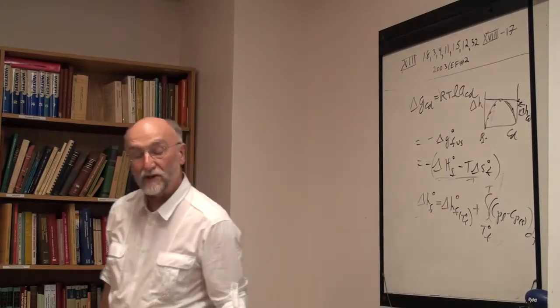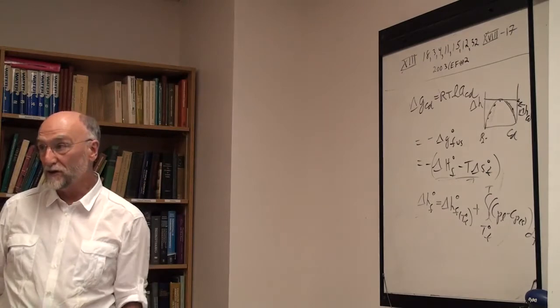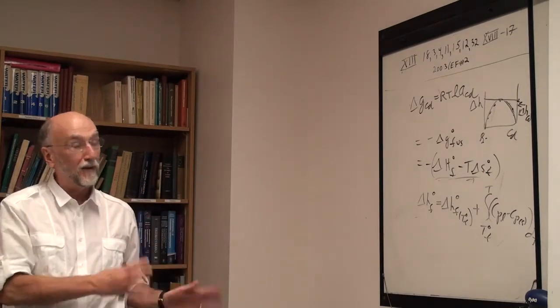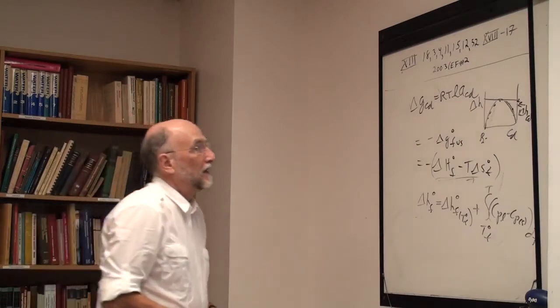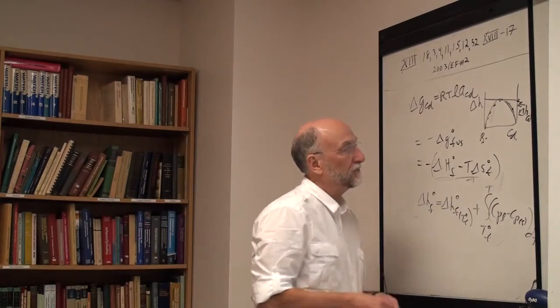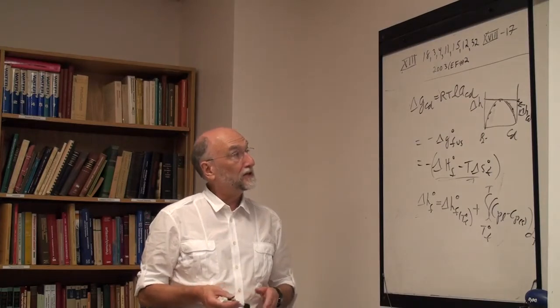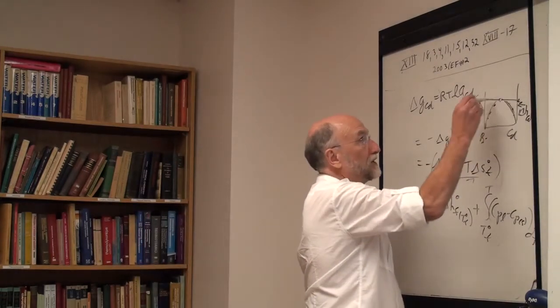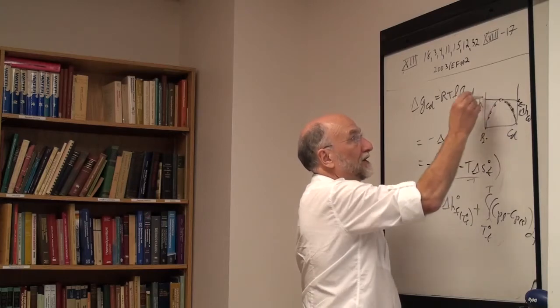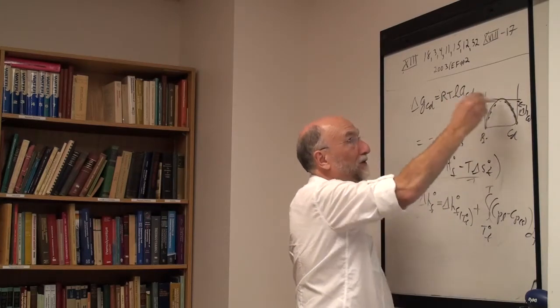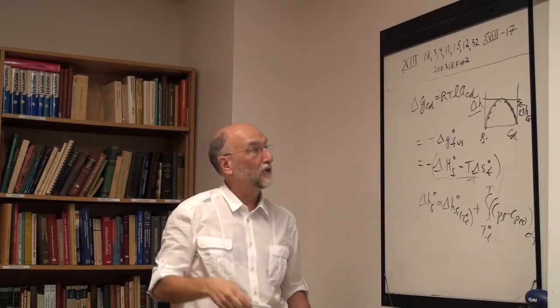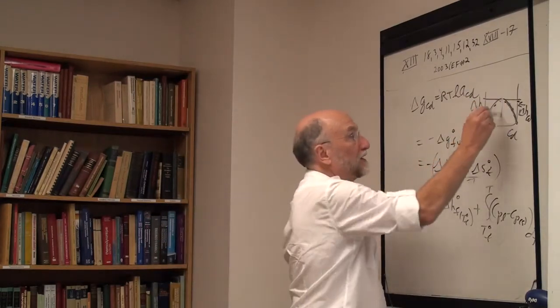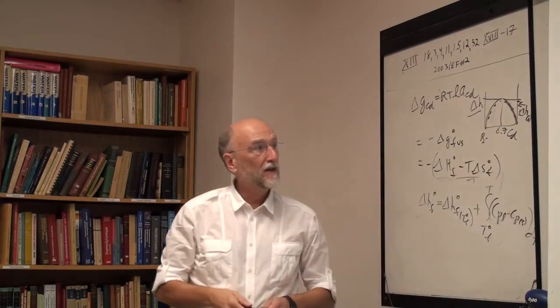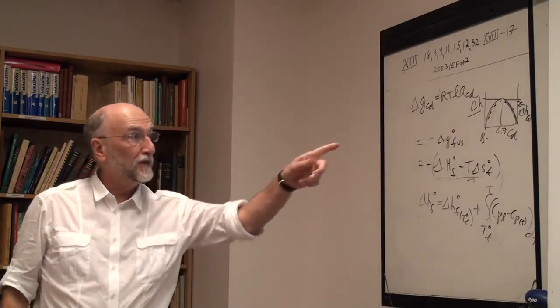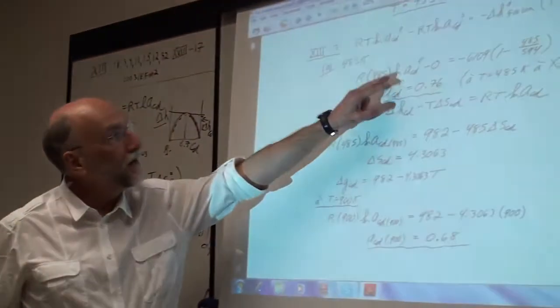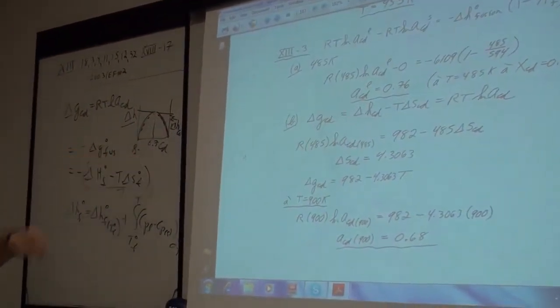So the partial heat of mixing of cadmium has been measured in an independent calorimetric experiment, not the phase diagram. The phase diagram doesn't give you that. Okay, so that's generally the way you would get the partial heat of mixing of cadmium. You don't measure it directly, you measure the integral heat of mixing at different compositions. Take the slope, where you fit this to a polynomial. You don't have to do it graphically, you fit it to an equation and get the slope. That gives you the partial heat of mixing of cadmium, and you do that at your composition of 0.7. And I've taken that from another experiment, that the partial heat of mixing of cadmium, when the mole fraction is 0.7, is equal to 982.